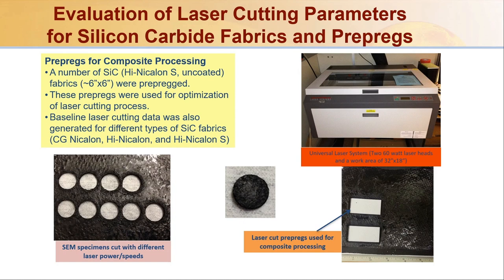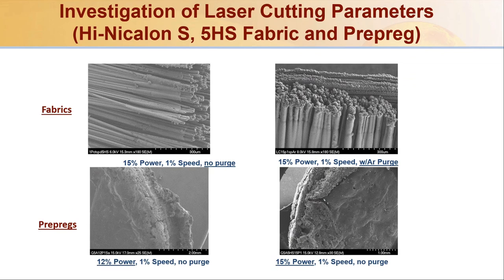The laser system we used has a two 60 watt laser heads, and has a work area of about 32 inches by 18 inches. On this chart, you see what really happens with the laser cutting. What you are seeing is a Hi-Nicalon S 5 harness satin fabric and the prepreg. On the top, you have the fabrics. They were cut using 15% power with 1% speed and no purge. And on the right, you have the same power and speed with the argon purge. You can see on the right side, due to the argon purge, some of the vaporized material actually went on and deposited on those surfaces.